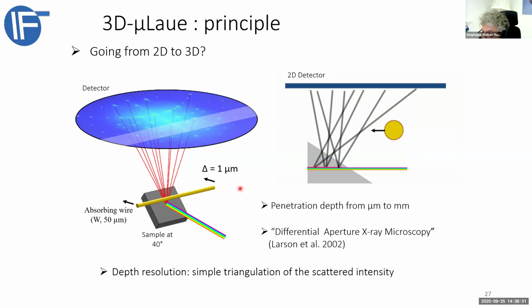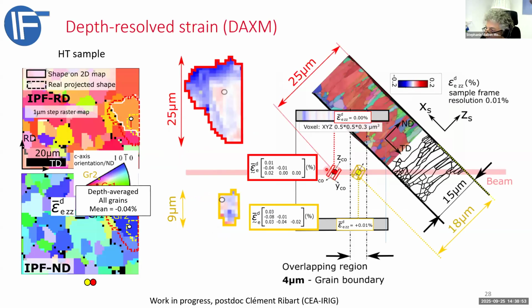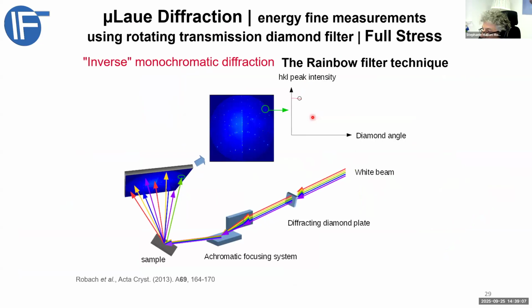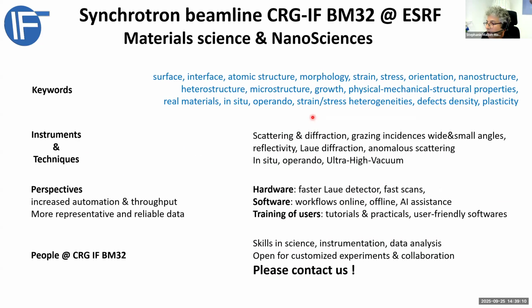You can have some depth resolved measurements simply if you do some additional measurement by making a travel of this wire, and then you can cut the intensity touching the detector, and then you can retrieve where the signal comes from. And then you can find the strain gradient inside the material. So it is a depth resolved strain map. Okay, so this is the energy measurement, and then I'm going to the conclusion.